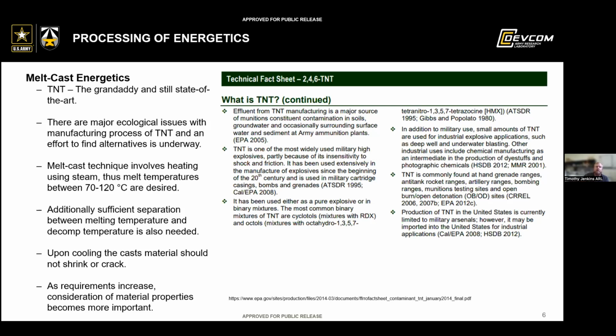And it turns out TNT, which is coming up on its 160th birthday, is still essentially the state-of-the-art melt cast energetic. And this is primarily due to the economics associated with making melt cast materials or melt cast energetics. It's very cheap to make TNT. Unfortunately, it is also an incredibly toxic process. And a lot of the sites that were used to make TNT in, say, World War II, where we were doing thousands of tons of this a year, are now Superfund sites, and they have a lot of issues with the toxicity in the ground.